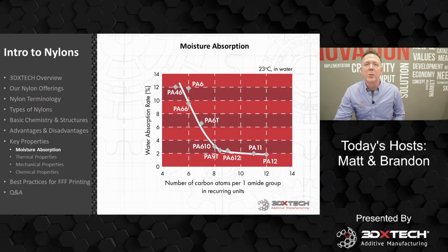So here's a graph about the moisture absorption. As you can see, and I alluded to it in other slides, the moisture absorption is directly related to the polymer structure. So if you have a smaller chain and there's more NH groups that have the affinity to the moisture, you can imagine you're going to end up with more moisture absorption. If you have a longer chain and fewer NH groups, or as you see in some of these terephthalics, they have that large benzene ring in the backbone to help protect from some of the moisture absorption, you'll end up with a little bit lower moisture absorption. And that will play itself out in mechanical properties and swell, what have you. But if you're going to be in a moist environment, then maybe say PA6 isn't the material for you if retention of mechanical properties long-term is what you're looking for.